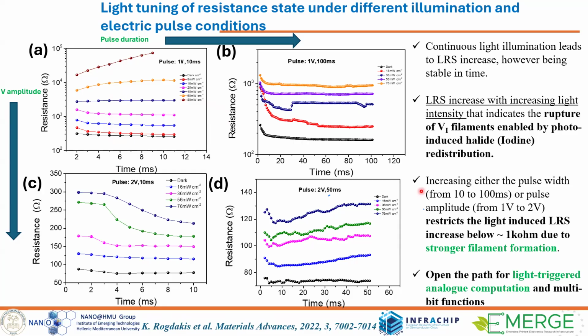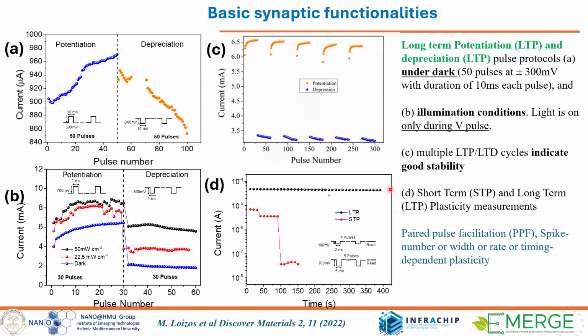Of course, we can tune the resistance states also by electrical pulses. Here, for example, we send 2 volts. Here we send 1 volt with a different duration. Typical synaptic protocols, potentiation process, depression process. Here we send positive voltages, for example, positive pulses. So we increase the current, while when we reverse polarity, we suppress the current. We can repeat this many times.